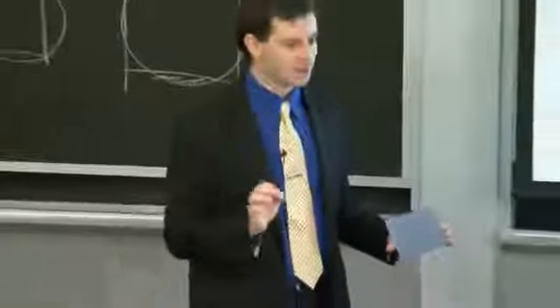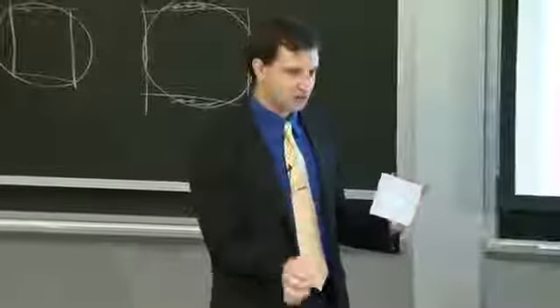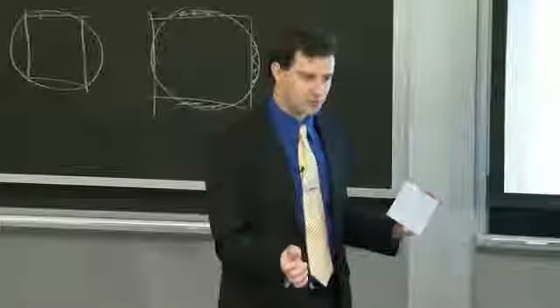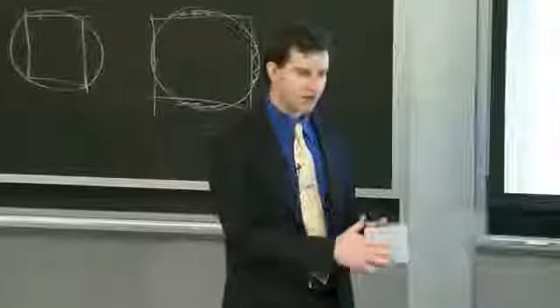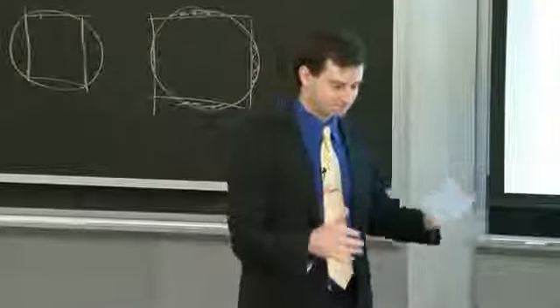Polycrystalline silicon in the silicon community has a very specific meaning. It means usually a plasma-enhanced chemical vapor deposited (PECVD) layer of silicon that has on the order of 1 to 5 micron diameter grains. So very, very small grained material, about 1/50th the width of your hair, maybe 1/10th the width of your hair. And to distinguish it from that really small grained material that would perform very poorly, one calls this multicrystalline silicon.